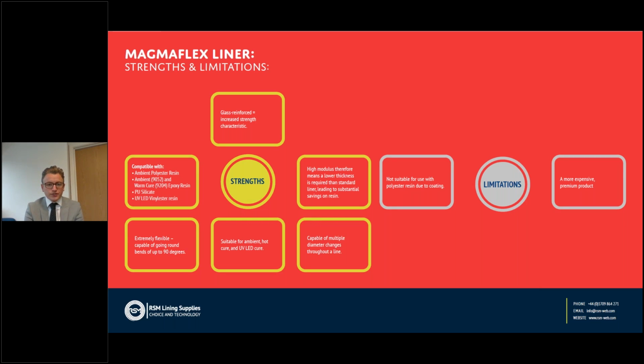The strengths and limitations. It's a glass reinforced liner, therefore this increases the strength characteristics that this gives. It also, because of the use of glass, reduces the amount of resin per meter that is needed compared to a standard felt liner. So if you were looking at a 100mm liner, you would usually need for a felt liner a litre per meter. With MagmaFlex, this reduces down to about 0.3 litres a meter. So a cost saving on the amount of resin that is required.